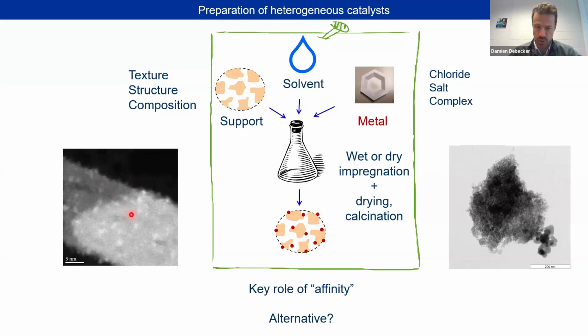That's an example where we managed to disperse tiny ruthenium particles of about 1 nanometer in size on the surface of a titania support, TiO2. But that's another example from my own PhD a long time ago, where we were trying to disperse molybdenum oxide on the surface of a silica alumina support. And you can see there that it was not really a success because we had patches of molybdenum trioxide crystals that we did not want in our reaction, in our catalyst, but they were there. So what I want to show you here is that with this kind of approach, sometimes it works, sometimes it does not. It's a challenge.